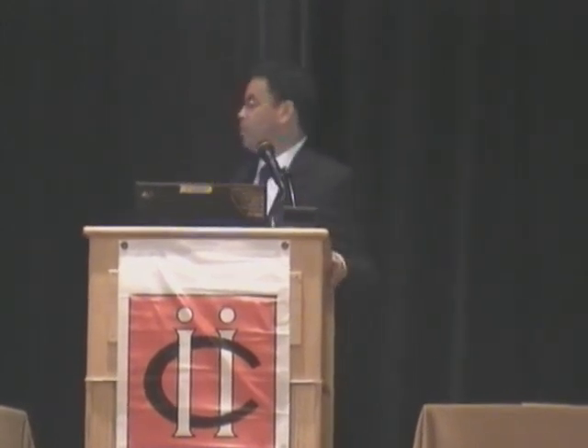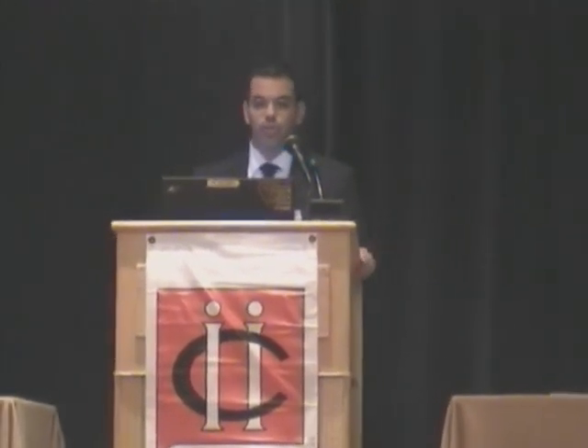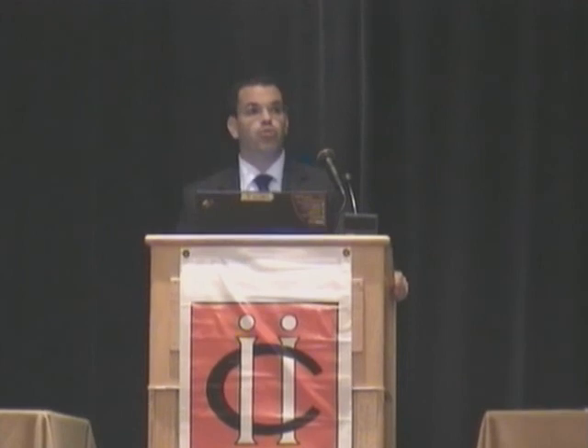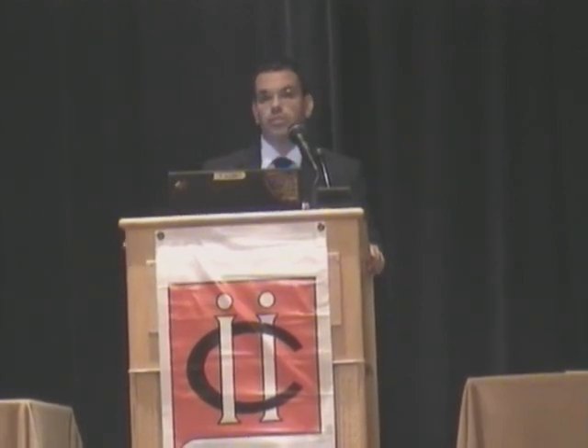The engineer gets the 3D model, puts a gate on it because he knows, and then you make the tool, you get the part, you've got like, I don't know, porcupine stuff sticking out, gates all around it, and now you start running with it. So now you start cutting gates, adding gates, nobody knows exactly what the part means. Multiple gates were used mainly to address the non-fill defects which we were encountering, mainly in pinhole castings. Those non-fill defects were caused by low shell and pouring temperature, which we were using to avoid micro-shrinkage and gas porosity phenomena, which led us to a low pouring temperature that inhibited feeding of thin walls, which resulted in micro-shrink.